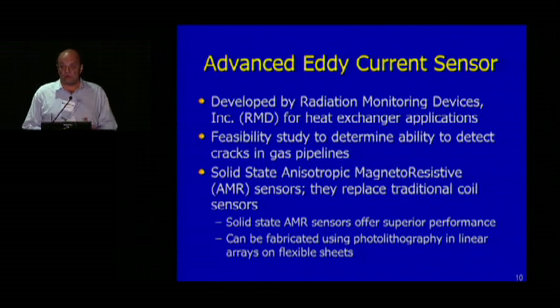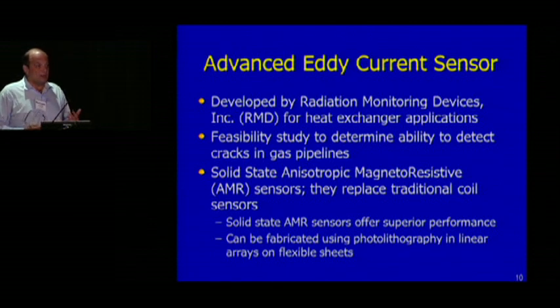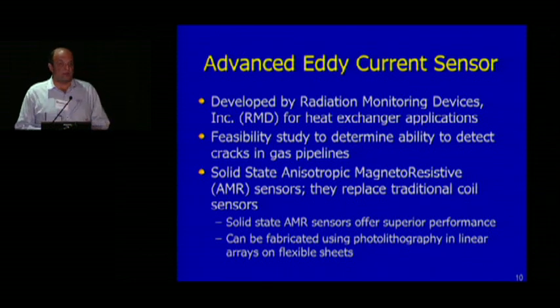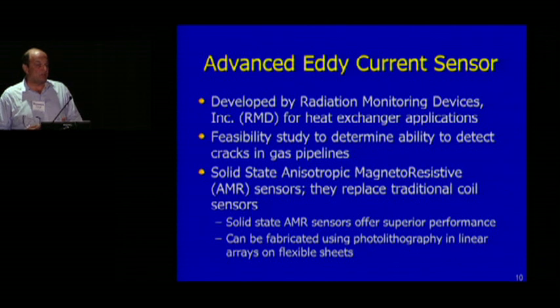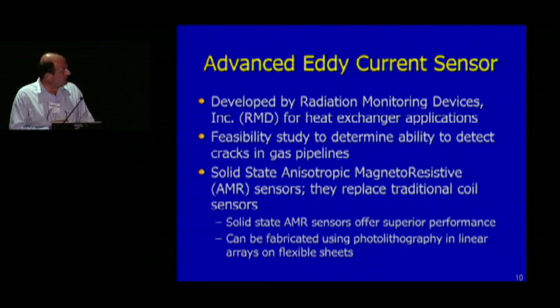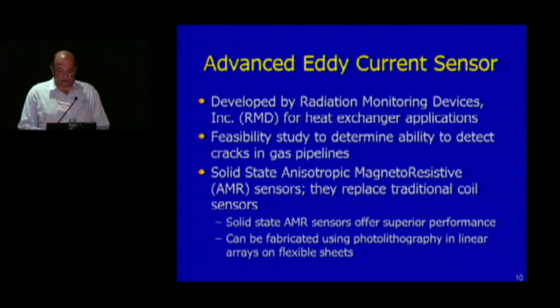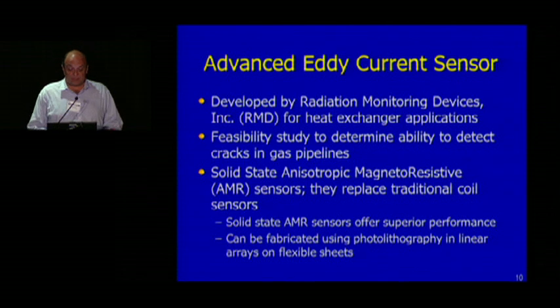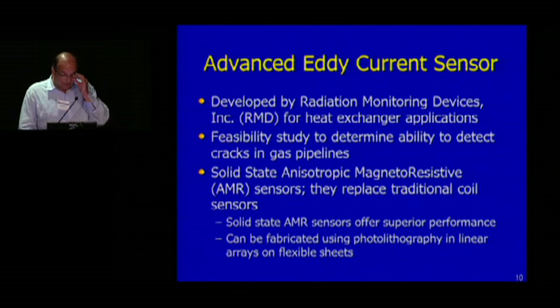Of course, this technology has been around for a long time, but the level of performance that you get from an eddy current sensor compared to an MFL sensor is lower, and a lot of that has to do with our ability to manufacture the coils that we use to create the eddy currents to a high degree of accuracy. So this new technology, called solid-state anisotropic magnetoresistive sensors, replaces traditional coil sensors. They're state-of-the-art and have clearly superior performance over traditional eddy currents. The beauty of them is that they can be fabricated using photolithography in linear arrays on flexible sheets.